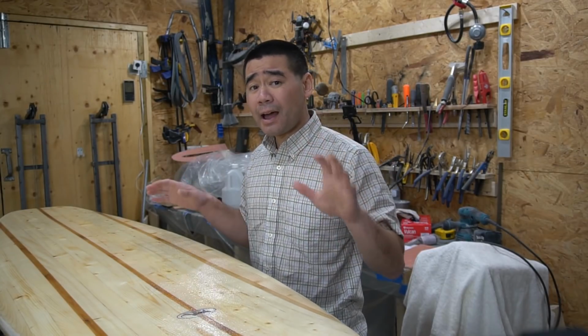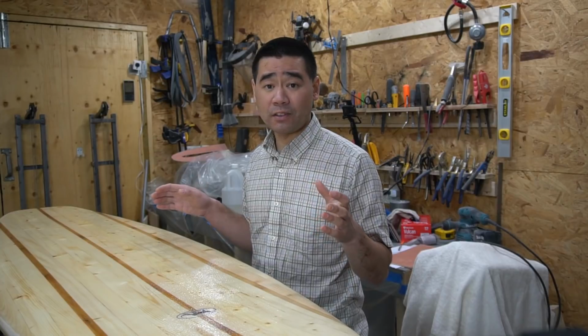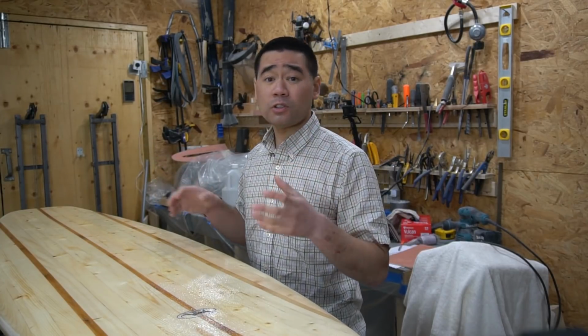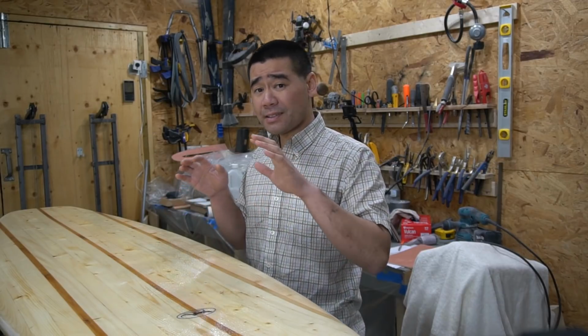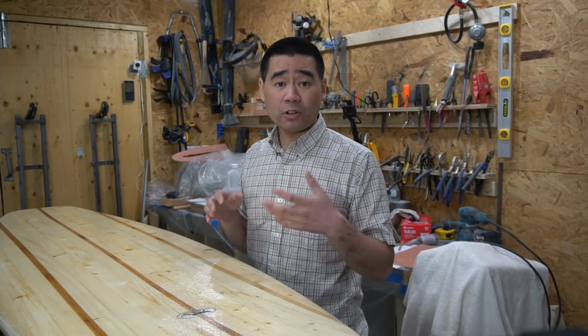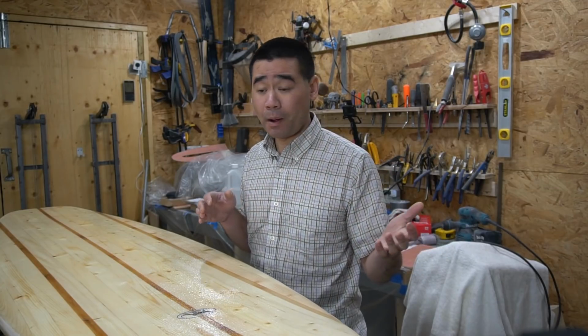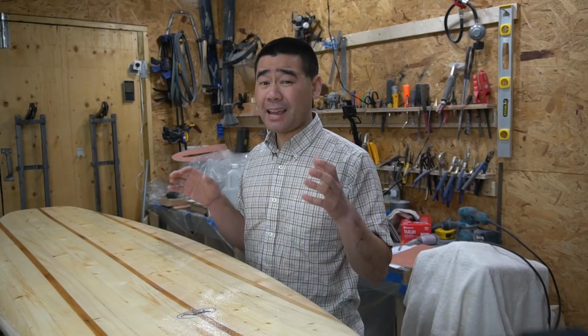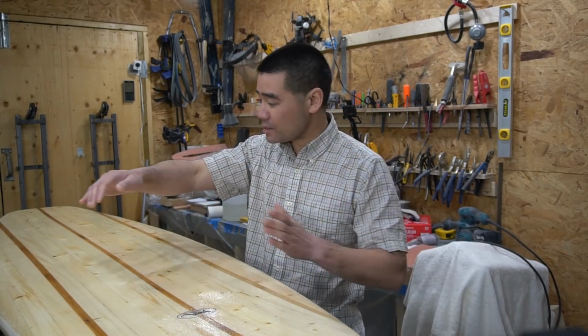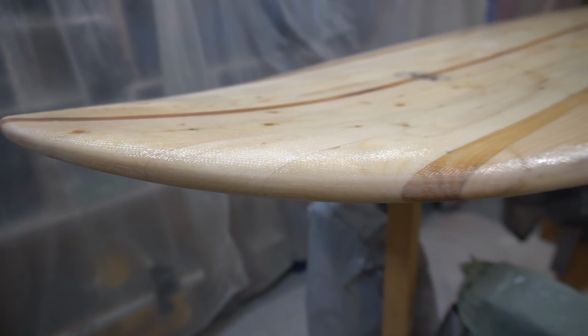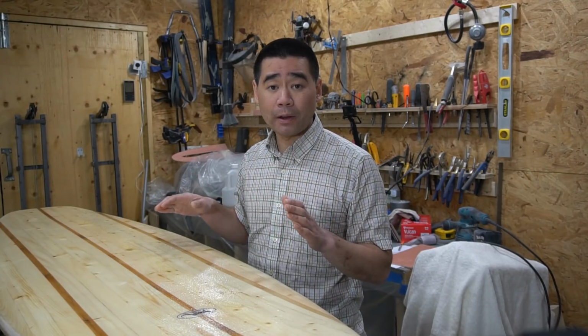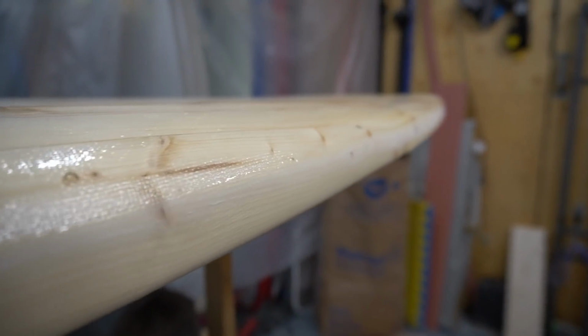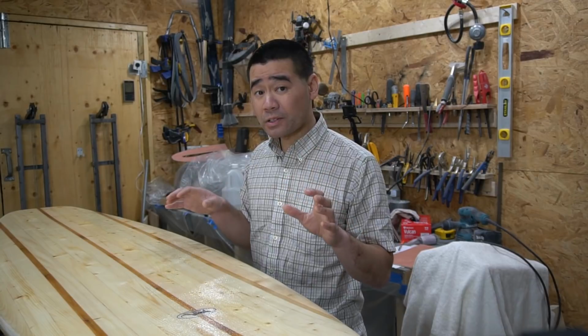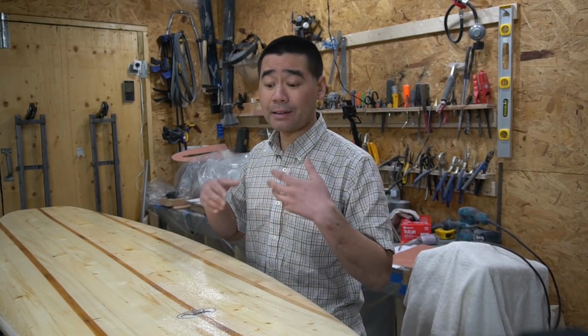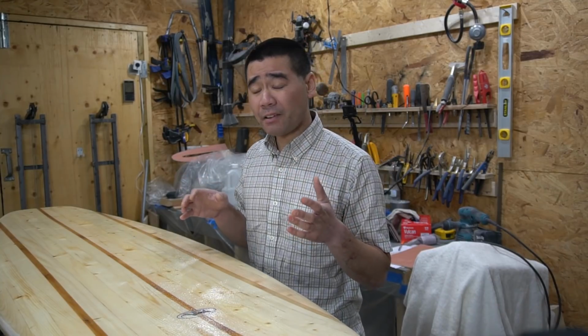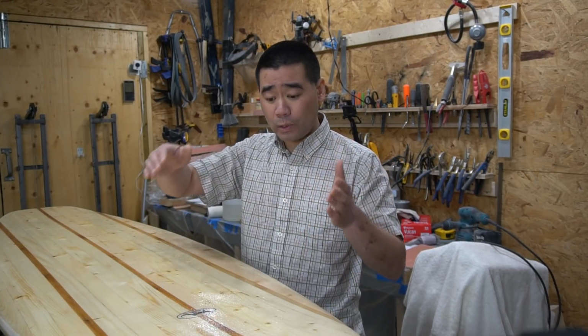Also, try to do all the glassing and the hot coating all within a few days of themselves while the epoxy hasn't fully cured, so you get more of a chemical bond, or else you're going to have to sand and rough up the surfboard a bit in order to get the additional subsequent layers of epoxy to adhere. Last item is sanding is super important. The rail that I spent some time sanding, the nose, and then anywhere where the fiberglass overlapped on the board, I made sure to blend and feather the overlapping layers of fiberglass nice and even, or else what'll end up happening when you go to hot coat and then sand the hot coat, you're probably going to have a higher chance of sanding into the weave of the fiberglass.